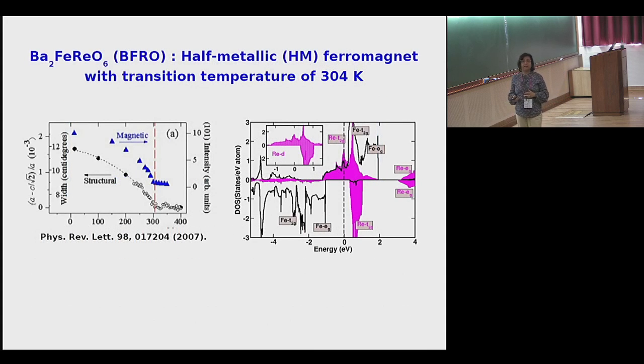Well, the compound that we worked on, and I will try to show this can be a general mechanism, is this particular double perovskite, Ba2FeReO6. This compound is a half metallic ferromagnet with a very high transition temperature, close to room temperature, which is shown here. You see it undergoes a structural phase transition from cubic to tetragonal associated with a magnetic phase transition, and both happen at very high temperature, close to room temperature.